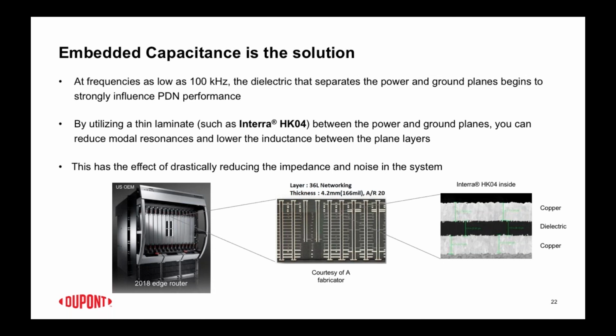It started out with a 50 micron, basically FR4 laminate as your power and ground plane. So as you get these planes closer together, you get better performance. But now we need better control of the power distribution network, so we'll be going to thinner dielectrics. Here happens to be an example of a 36-layer networking board, and you can see the very thin layers that are inside the board at multiple locations. It basically consists of copper, a dielectric, and another piece of copper.